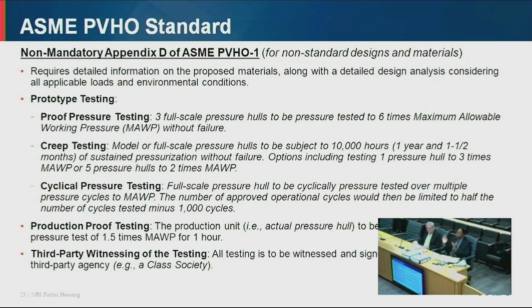So once you conduct the prototype testing, you have qualified the prototype. The next thing is you build the production unit, and thereafter you'll do a hydrostatic pressure test to 1.5 times the design pressure, and then you'll maintain the pressure for 1 hour. Now for this case, all the testing needs to be witnessed and signed off by a third-party independent agency such as a class society. Okay, so these guidelines provide very, very clear requirements for non-standard designs and materials. You can follow these guidelines anytime you have non-standard designs or materials. So there is a mechanism in the industry for qualifying non-standard designs and materials. Next slide, please.